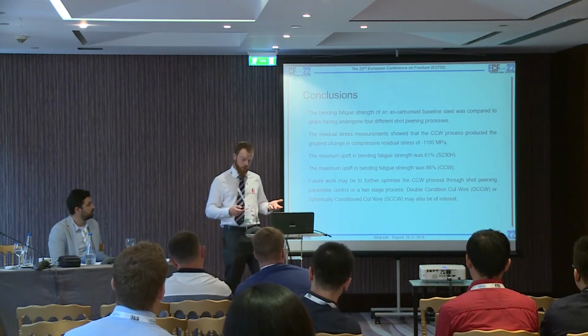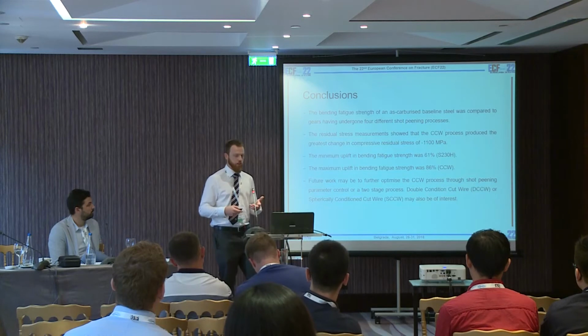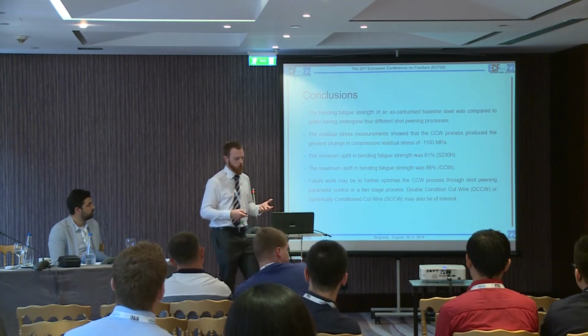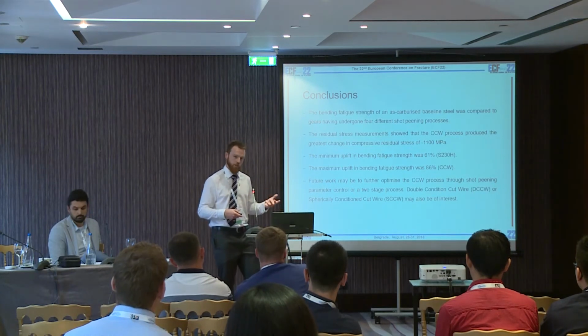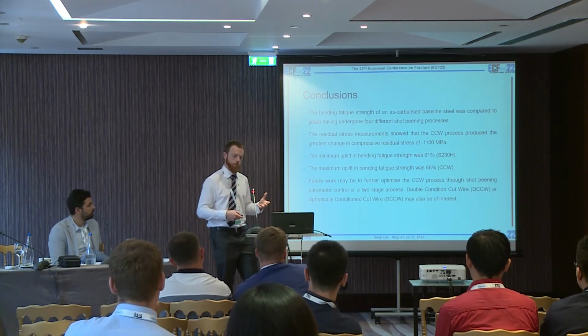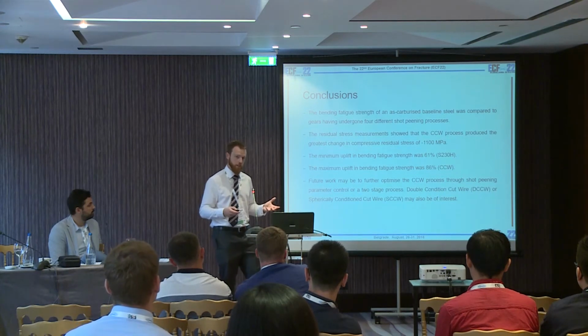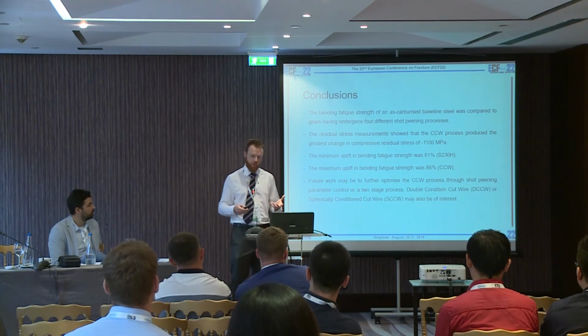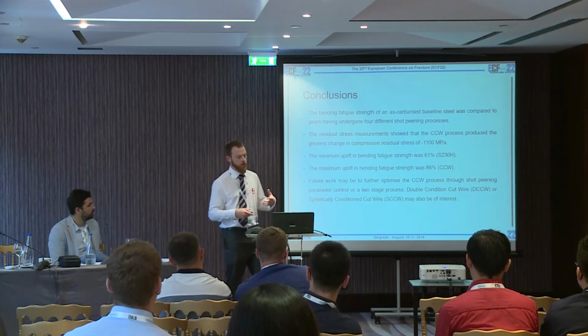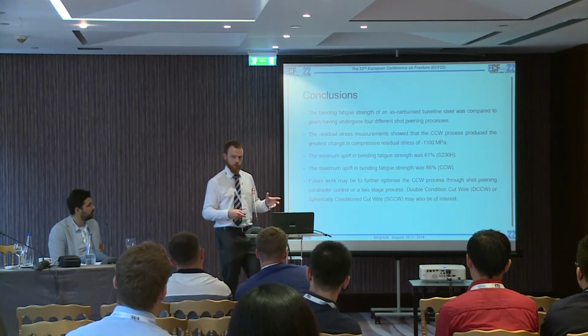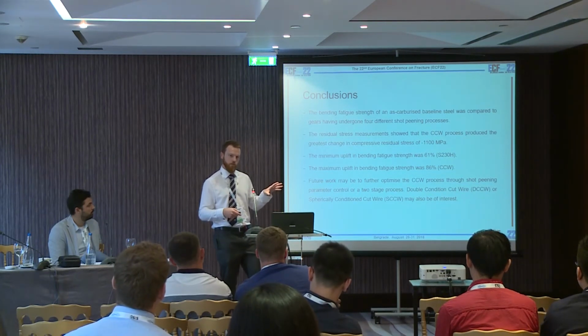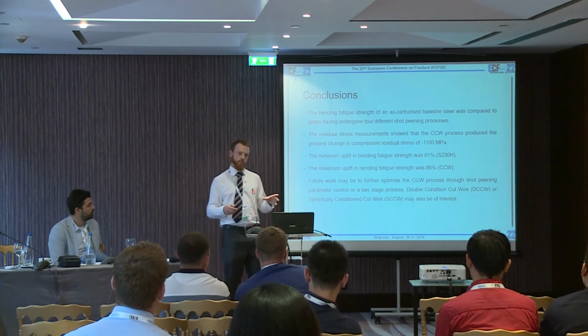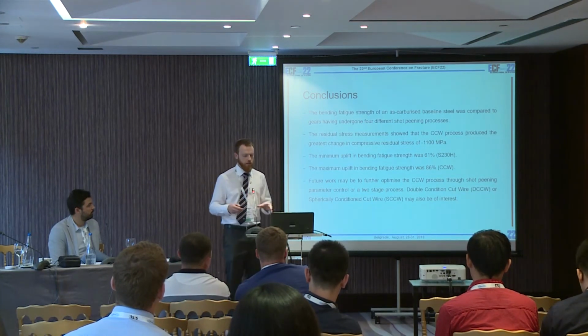So some conclusions. We've looked at the bending fatigue strength of as carburized baseline steel and compared that to 4 shot peening processes. We've looked at some residual stress measurements, and we've shown that the condition cut wire gave us the greatest change in compressive residual stress over the broadest peak of minus 1,100 megapascals. The minimum uplift in bending fatigue strength was 61% from one of the standard shot peening processes. The greatest uplift is 86%. So we compare that back to what we discussed from ISO 6336, where they're suggesting to the gear designer that we see a 0 to 10% increase.